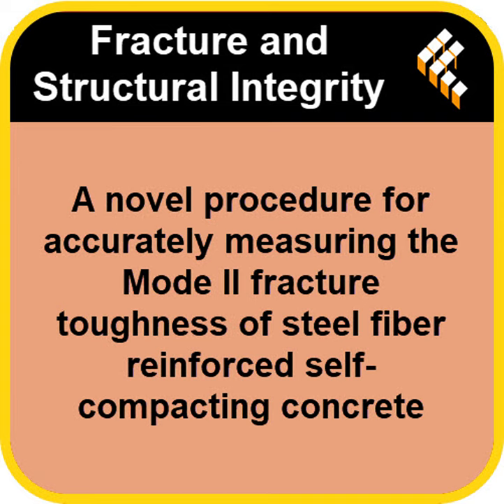And for FRSCC, that measurement has been problematic. You mentioned the traditional test uses a double-notched cube specimen, the DNC, but prepared with a through-thickness crack, TTC. What's wrong with TTC? Okay, this is really the heart of the matter. With FRSCC, almost all the extra toughness, the resistance to the crack growing, comes from the fiber bridging effect. Right, bridging. Yeah, as the crack tries to open or slide, those steel fibers span across the gap. They literally hold the two sides together like tiny ropes absorbing energy. Okay, so the fibers crossing the crack are the key.